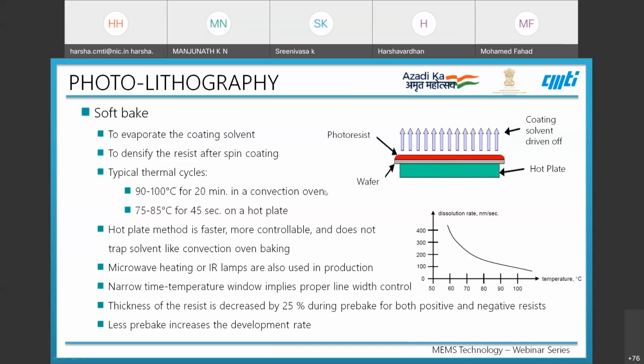So typical thermal cycles that can be used for soft bake vary from 90 to 100 degrees for 20 minutes in a convection oven if we are using that methodology, or 75 to 85 degrees for about 45 seconds on a hot plate.